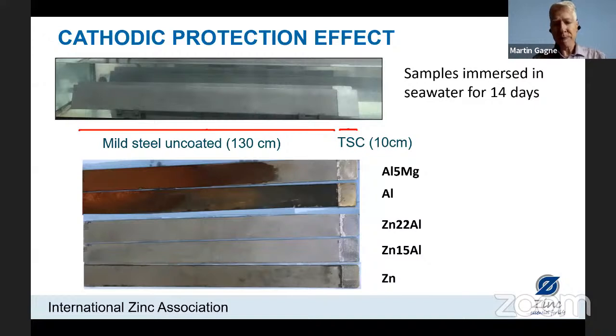The bottom three are zinc alloys and pure zinc that is available for thermal spraying: zinc 22% aluminum, and more common is the zinc 15% aluminum, so this would be 85% zinc, 15% aluminum, and then the pure zinc. Now here we can see that small 10 centimeter coating has fully protected 130 centimeters of exposed steel. So this is just a very graphic illustration of the galvanic corrosion potential of zinc for protecting steel.